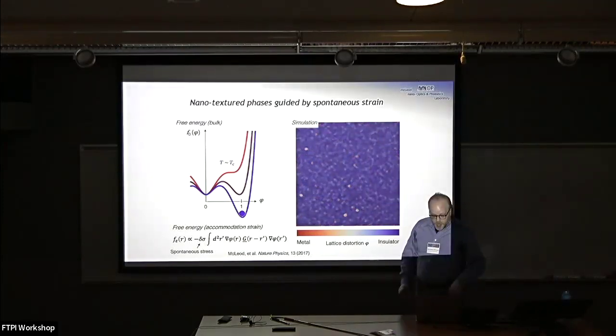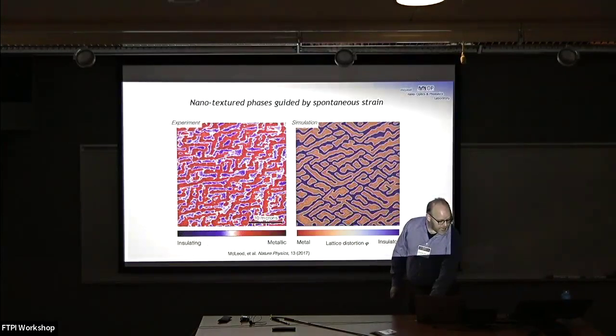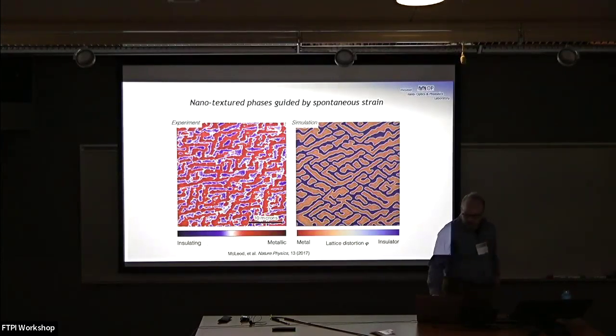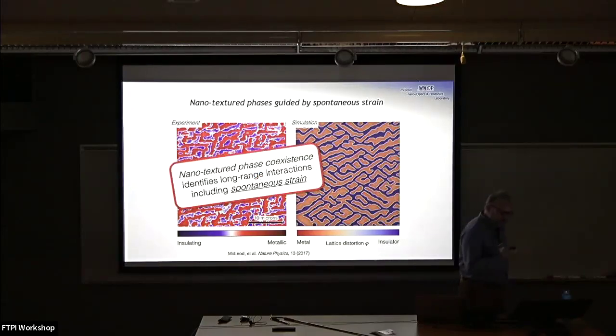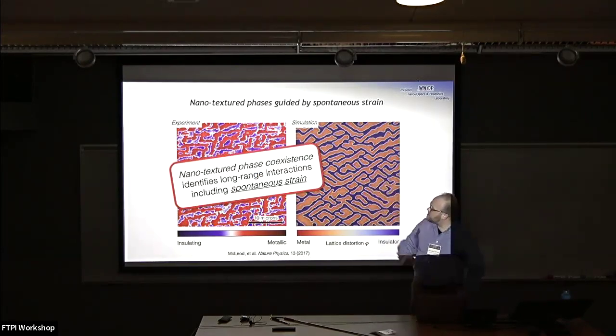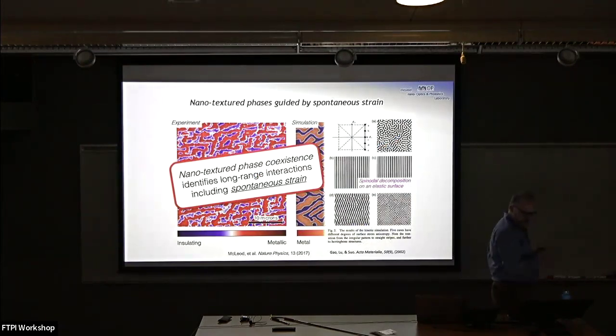All right, very good. So I want this slide or slides to just serve as a reminder that generically, if my order parameter is coupled to strain, magnetism, this microemulsion is something that you ought to expect. And in sufficiently clean materials, you'll see, although the order may be hundreds of nanometers, the patterns themselves may persist across the entire material. So in our case, long-range interaction and spontaneous strain are what our imaging of these domains is identifying and actually quantifying.